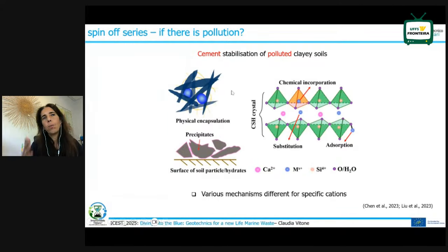Now, the two spin-off series. So what happens if we have pollution? It is very well known in the literature that cement stabilization can help polluted clay soils, because cement acts by means of various mechanisms which depend also on the different cations: we have physical encapsulation, we have precipitation, which is very common, for example, for lead. We have substitution, adsorption. So we have a lot of processes which cement can induce to reduce the pollution in the sediments.